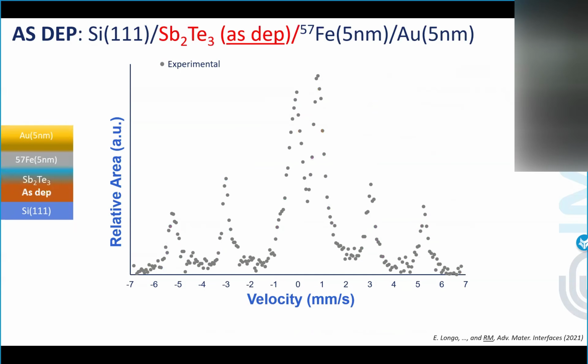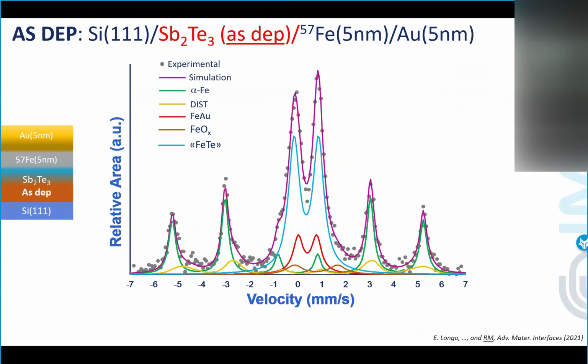But that was the astonishing result, which gave us the first very important information from the Mössbauer: when you grow your iron layer on top of an as-deposited topological insulator, there is a huge contribution from the center coming up. And this is bad, because if you want to develop processes for spin-charge interconversion at this interface, of course, you don't want to have paramagnetic phases at the interfaces.